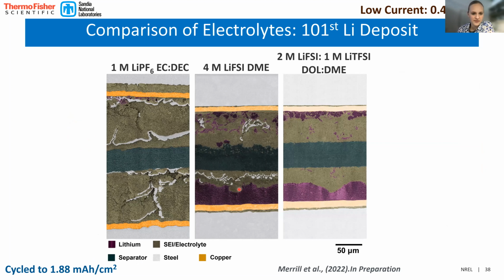In the 4 molar lithium FSI and DME, you can see that there's still capacity left, there's still ability to plate and strip, but there's a lot of SEI that's formed, and also in the concentrated bisalt solution, it looks fairly similar, but less reactive to the separator than we saw with the DME situation.